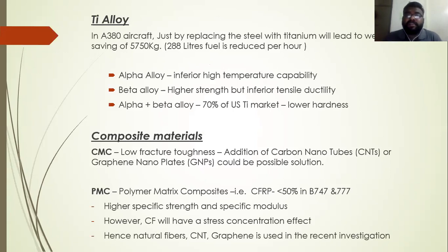Similarly, titanium alloys. Let me say one important parameter which highlights the titanium alloy applications. In the A380 aircraft, just by replacing steel with titanium, a weight reduction of 5,750 kgs can be saved. That in turn saves 288 liters of fuel per hour. Just imagine how much the application of titanium contributes towards fuel consumption.